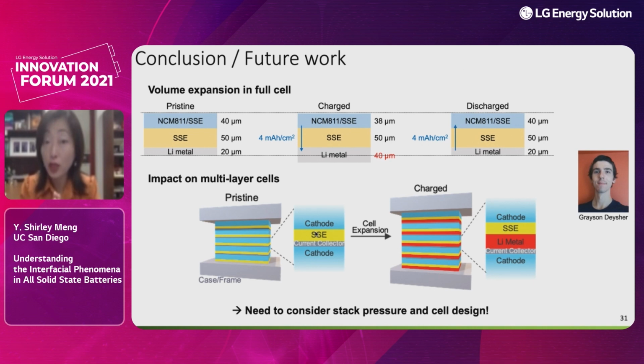So we do some kind of thought experiment, right? If you just have low loading for the NMC cathode, 40 micron, and it's only 4 milliamp hour per centimeter square, and you shuffle 20 micron to the negative electrode side, the negative electrode side will become 40 micron. But the solid state cathode is actually an intercalation material, so it will only have 4 or 5% volume change. So net, this cell will want to grow in its dimension.